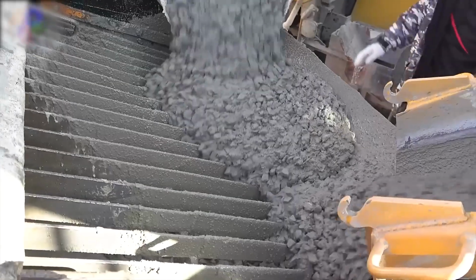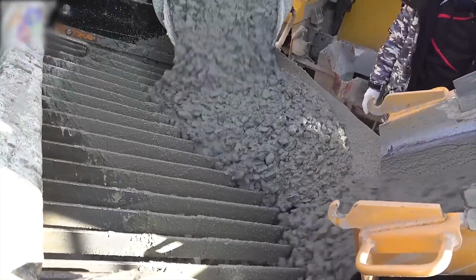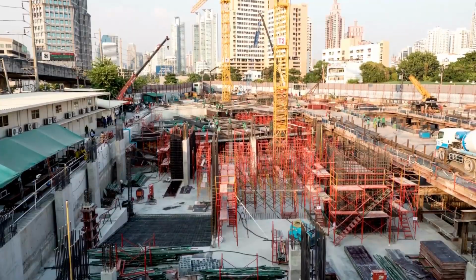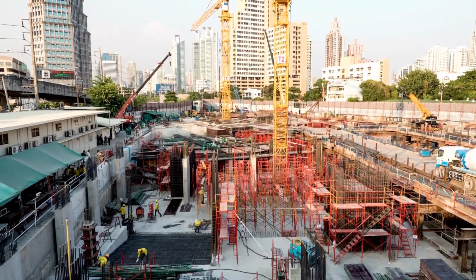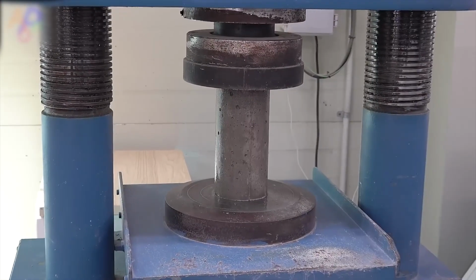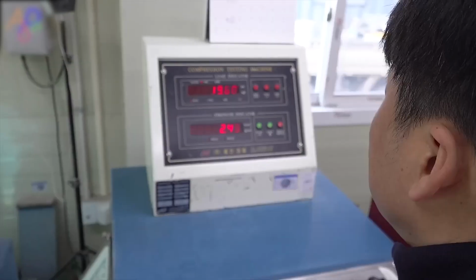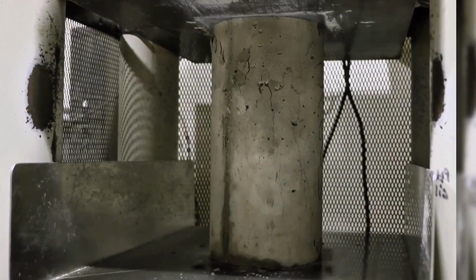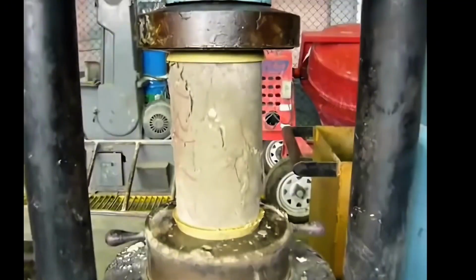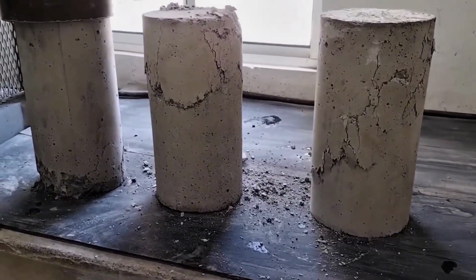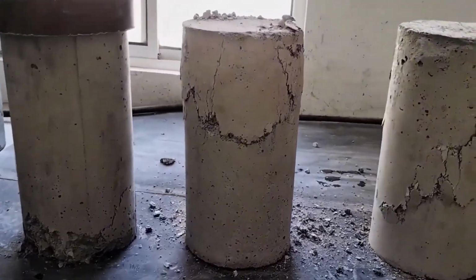The fracture pattern and the pressure at failure determine whether the batch met its specified compressive strength, usually measured at 28 days. A uniform cone-shaped fracture is a pass. A shear fracture along a single diagonal line can indicate problems in the mix proportions or curing conditions. These results are legally tied to the delivery ticket and kept on file.